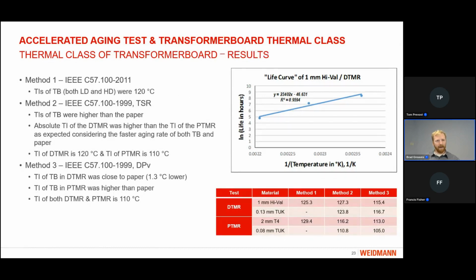So using those three methods of analysis, we end up with a variety of results summarized in this table here. The first thing is looking at method 1. We're using, again, the 2011 version of this standard. We have the thermal index of the transformer board, both high and low density, being 120 degrees C. As Tom described previously, using this method, we look at the thermal index being the point at which the minimum life expectancy curve crosses the 20,000 hours. For these materials, for the distribution ratio, that was calculated at 125, and for the power ratio, that was 129.